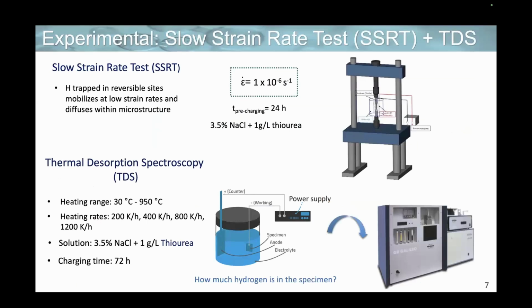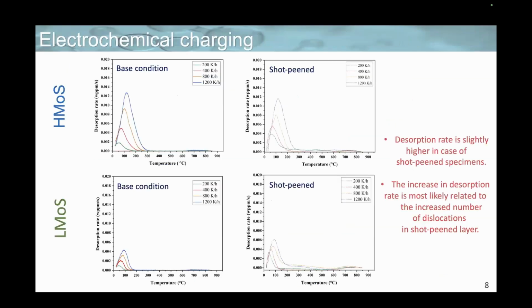Then to compare the mechanical behavior of the materials in air and once they are exposed to the hydrogen environment, we performed slow strain rate tests with pre-charging and in situ charging during the loading. And also we electrochemically charged the specimens, and by using thermal desorption spectroscopy, we obtained the desorption curves.